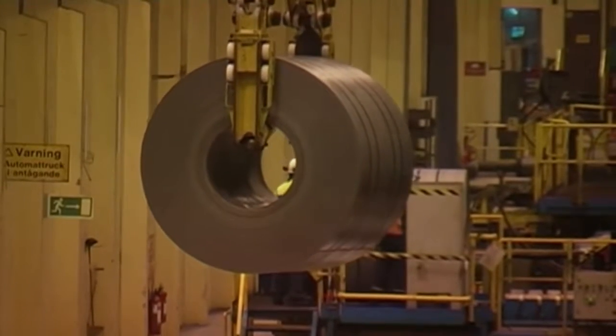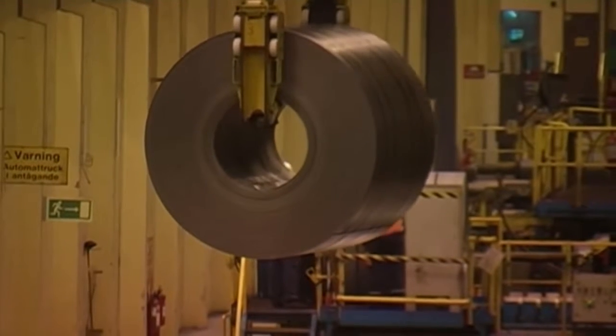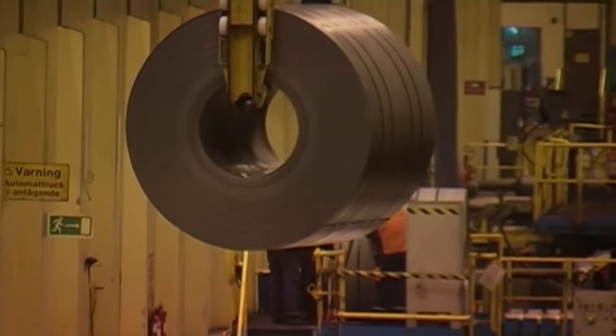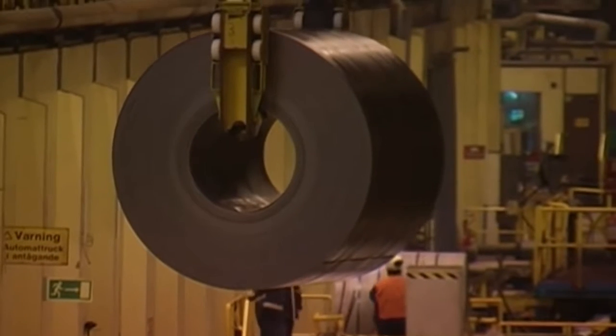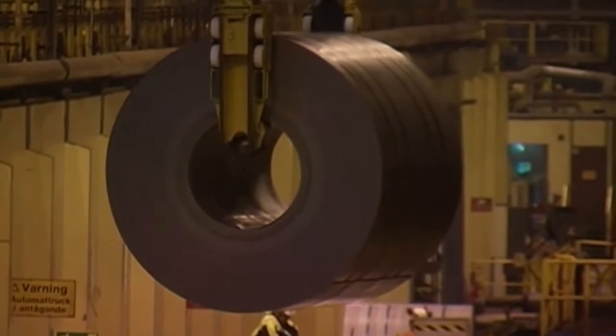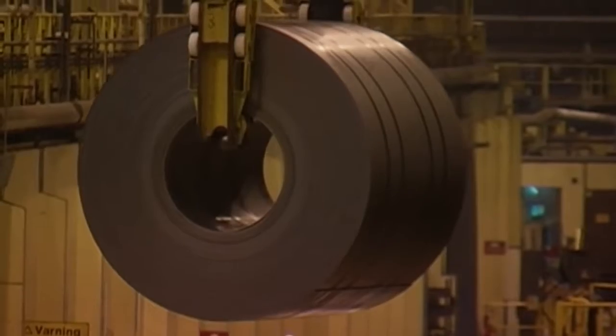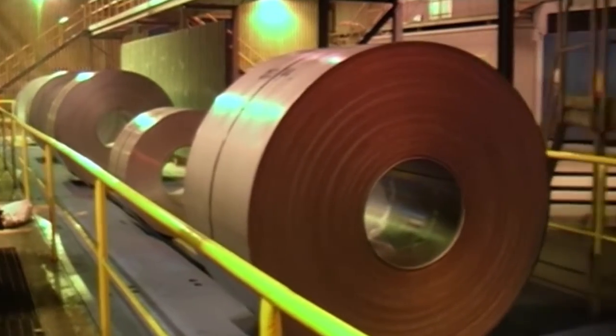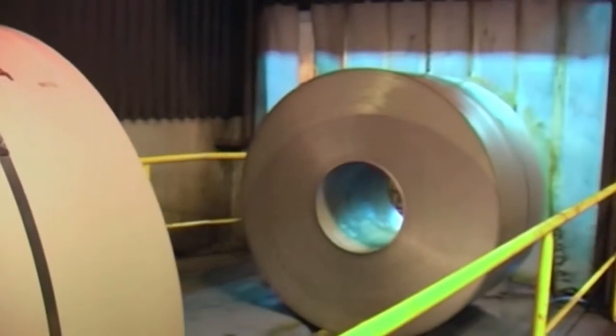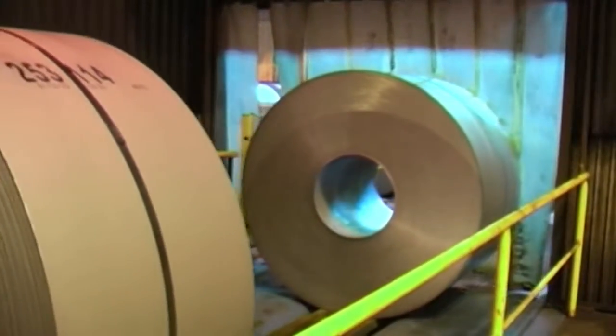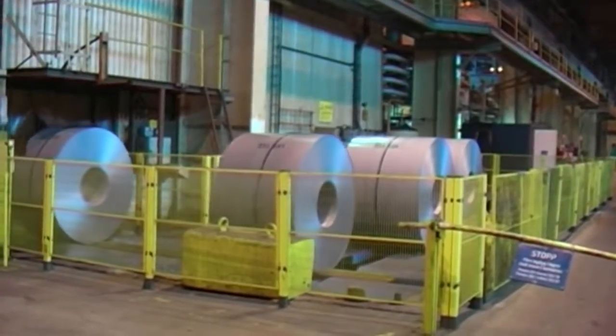The cooling rate is adapted to each strip to produce the appropriate microstructure and material properties of the end product. When the strip has passed through the cooling section, it's coiled in. The temperature during coiling varies between 150 and 750 degrees centigrade, depending on the properties assigned to the material. After coiling and the subsequent cooling, the strip can be sold directly to the customer or undergo additional processing stages, for instance, cold rolling.